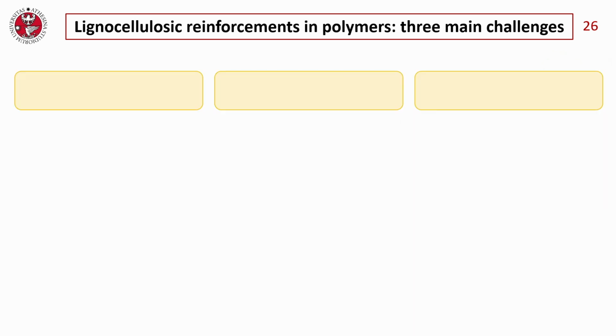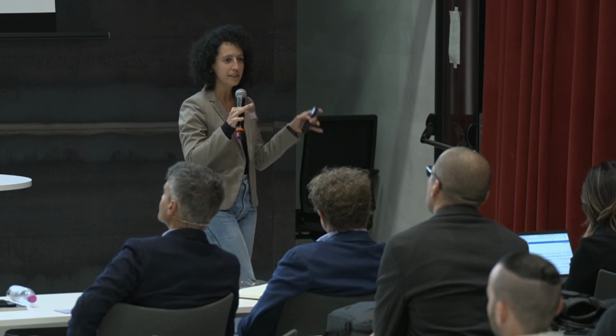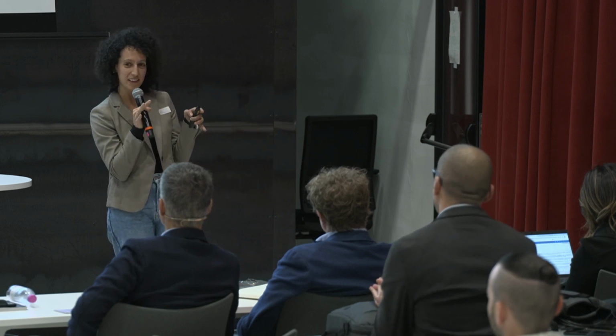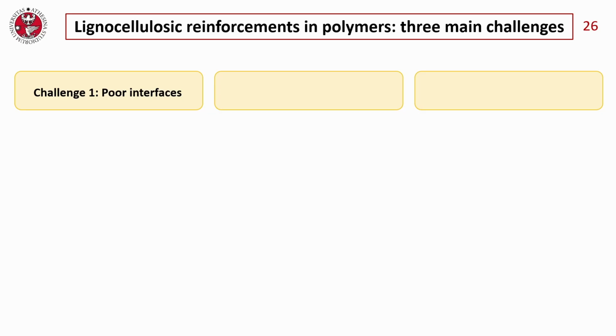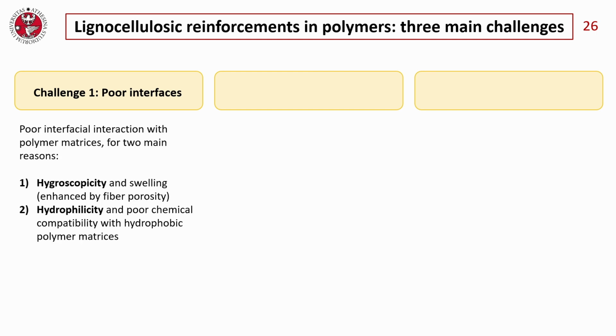My presentation will focus quickly especially on the challenges, no? And what we can do to tackle these challenges. So, to summarize all the challenges that natural lignocellulosic fibers bring, I think that they can be divided into three main groups. The first challenge is the poor interfaces with the polymer matrices. In fact, they are hygroscopic and hydrophilic. Therefore, they have a poor interfacial interaction with polymer matrices, which are mostly more hydrophobic. But they also absorb water, and this causes swelling of the natural fibers, which further degrades the interface.